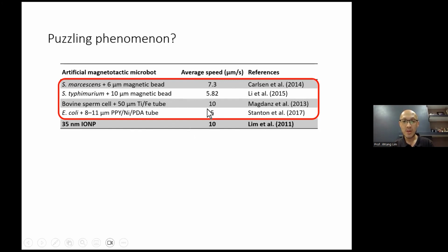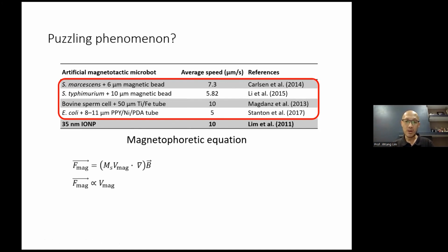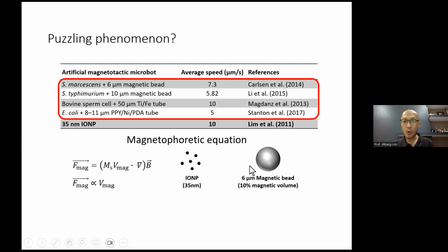And why is this actually causing trouble? Because if you think about it, the magnetophoretic force is defined by this equation and is proportional to Vmag, the magnetic volume of the particles that you use. So in other words, the magnetophoretic force is directly proportional to magnetic volume. If you compare 35 nanometer particles and a 6 micrometer magnetic bead, even with only 10% of the volume of the bead being magnetic and 90% non-magnetic, we are still talking about a 500,000 times difference compared to small iron oxide nanoparticles.